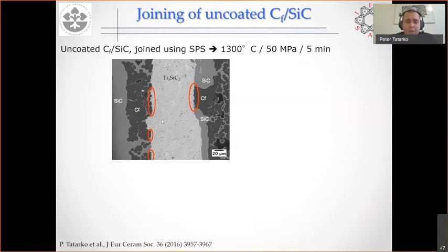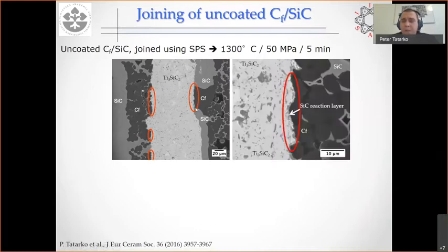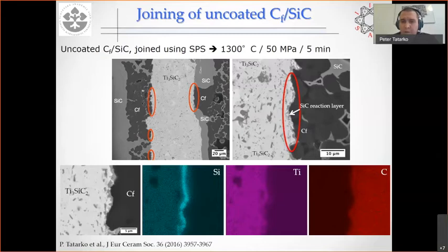Here I'm coming to the results for uncoated samples. In this case, we have not one interface only, but two interfaces. One interface was between the silicon carbide matrix and our joining filler, and the other between carbon fibers and the joining filler. In the case of the interface between silicon carbide and the filler, the situation was exactly the same as before. But in the case of the carbon fibers, the very important thing is that we were worried about damaging the carbon fibers, of course. But you can see here that these SEM images and also EDX analysis confirm that the filler reacted with carbon from the fibers and formed an in situ silicon carbide reaction layer. Once this layer is formed, it stops further diffusion. So you don't get damage to the carbon fibers.